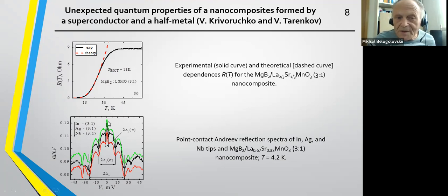What was observed is that the superconducting transition starts from the critical temperature of magnesium diboride. As a superconductor, magnesium diboride was used, with a critical temperature near 40 K. And after that, there is a broad transition, and the shape of this transition was explained by the Berezinskii-Kosterlitz-Thouless transition effect. So it was most probably the first observation of such a BKT transition in a three-dimensional sample. And it was explained that this transition is at the shell around the superconducting grain.